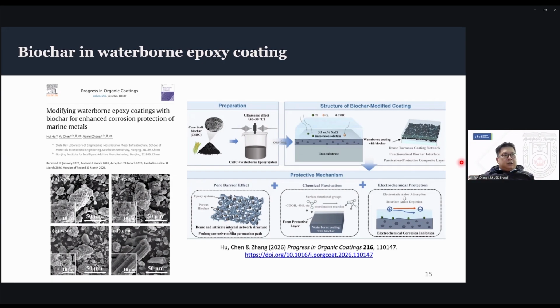So where biochar is quite useful is that it can confer some mechanical strength. It has high surface area, a microporous structure, so you can play around with ideas to use the biochar to capture corrosive species due to the high ion adsorption properties of the biochar.